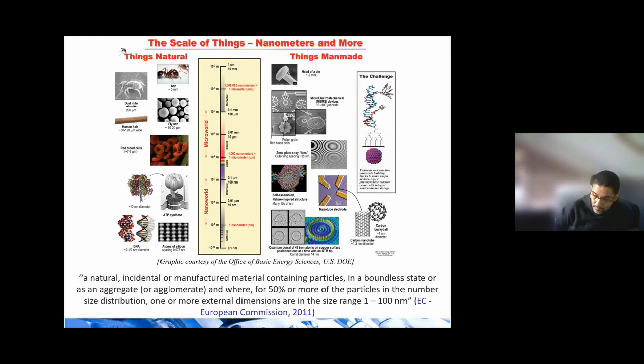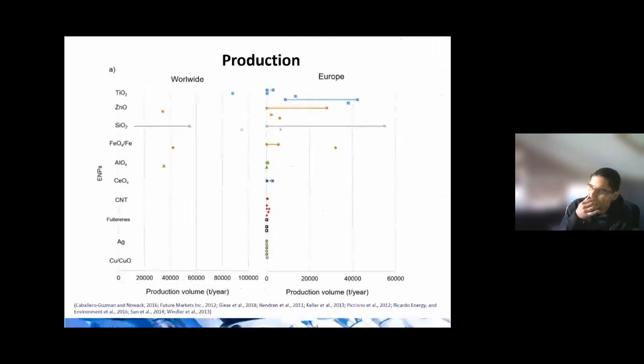And sometimes, if you go to some literature, you see that in water technology we define suspended particles as particles that can be retained by a 0.1 micrometer filter. So officially, we measure particles of 50 nanometers in the lab, and even though we still consider them suspended particles, according to some formal definitions these particles can already be considered dissolved. That's a nice point, because even at this nanometric scale, you start to have a borderline between what is dissolved in your water and what is actually suspended in your water.